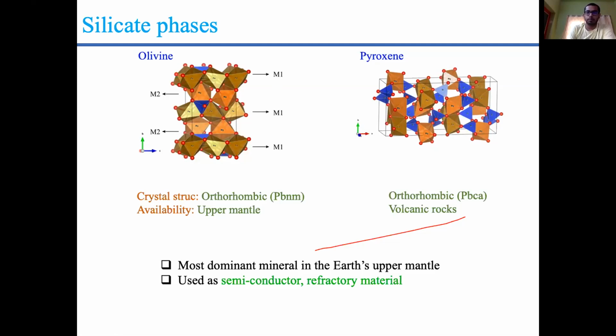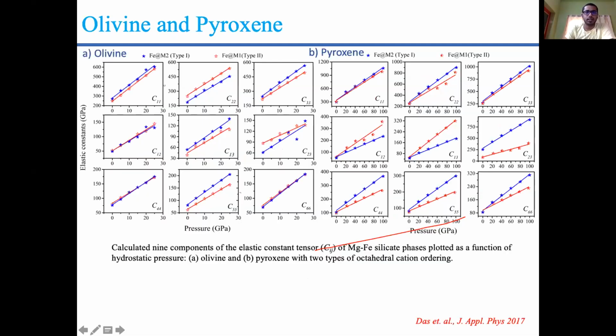So my aim was to study the effects of cation ordering in these octahedral sites on the mechanical and electronic properties of these mineral phases. I again start with the elastic constants. I plotted a lot of elastic constants here because this is an orthorhombic system. I have to calculate the 9 elastic constants for each phase. On the left hand side the 9 elastic constants of olivine are plotted, whereas on the right hand side you can see pyroxene. The main thing to observe here is the C55 elastic constant.